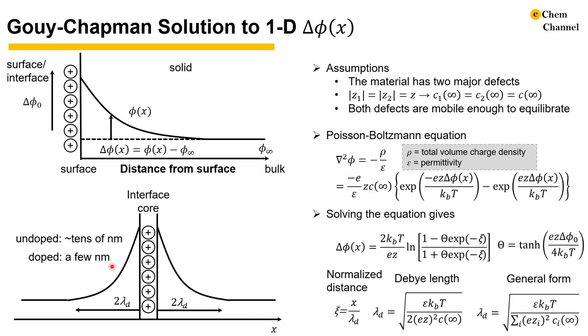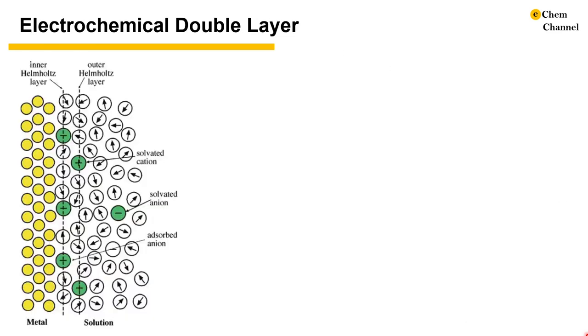For a grain boundary, we will have a space charge layer that spans approximately four times the Debye length. The fact that the Gouy-Chapman model was originally from electrochemistry but can be applied to the space charge layer brings the questions how similar is the space charge layer to the double layer, and how good is the Gouy-Chapman model at describing the double layer.